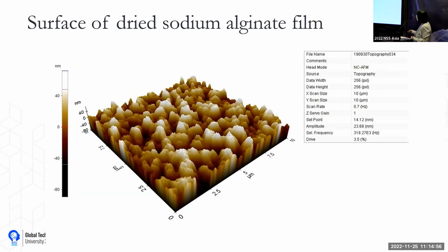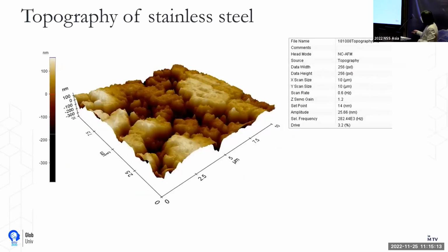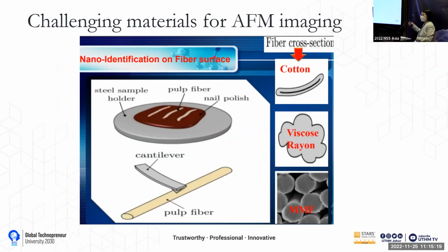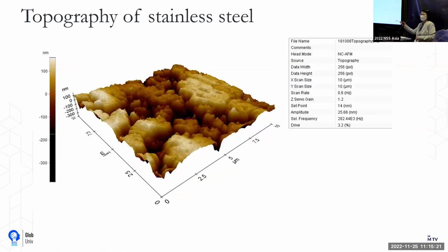Okay, so this is a hydrogel that has been dried for biomaterial application. So a sodium alginate thin film that indicates the porous structure of the sodium alginate, right? A topography of a stainless steel. Yeah, so it's not that homogeneous actually in nanometer structure. So these are all very simple materials to us because they are just thin films, nothing interesting.